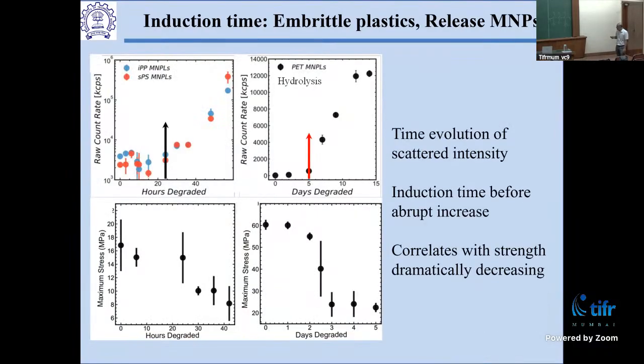Okay, so what really happens here, right? So what's happening here is if I now look at these materials, so this is now as a function of time. This is data for isotactic polypropylene, syndiotactic polystyrene. These are the ones that do give you scattering. And I look at the scattered intensity. What I notice is that when I put this film in there, I put the film and just keep watching this thing as it evolves. Initially, I don't get any particles. But there is sort of a critical time, some kind of an induction time. And beyond that induction time, I see the formation of these particles.